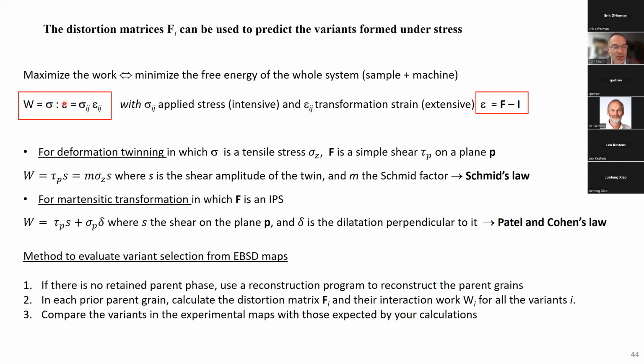The interaction work is calculated by that. If you apply a stress to a material, you calculate the stress value multiplied by the deformation matrix element. You apply this formula, okay? You multiply each element of the stress by each element of the deformation. You multiply them, and at the end, you make the addition between all these products. Here, the deformation is a deformation relative to the transformation. It means that it's a distortion minus identity.